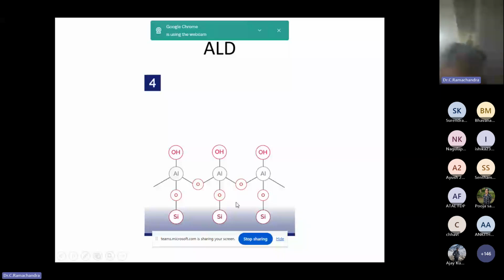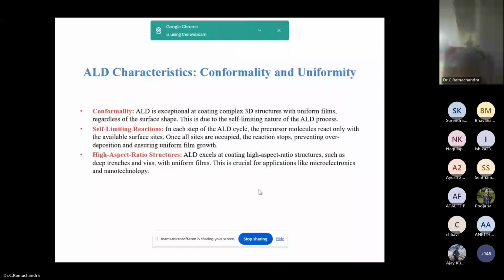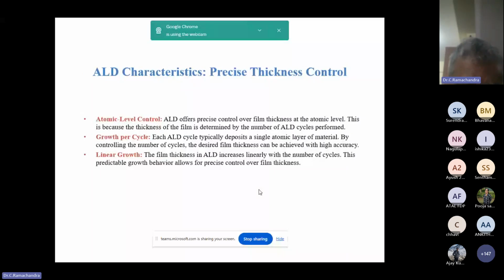So, conformality and uniformity. It is very, very conformal. Many complex 3D structures have been deposited using it. It is a self-limiting reaction, so we don't have to worry about thickness control. Only one layer is deposited. And many high aspect ratio structures have been deposited because it is a surface reaction. It gets absorbed by the surface and the reaction happens only at the surface. Precise thickness control, because there is no variation, only one atomic layer, and it is linear growth.